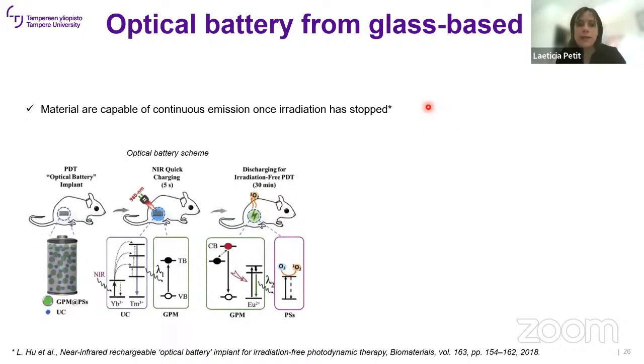The reason we are working on that is because we want to make an optical battery. So a few years ago, there was this very nice paper on a near-infrared rechargeable optical battery implant. The team worked on upconverter crystals, and they mixed them with persistent luminescent particles. Persistent luminescence is when you have luminescence after stopping the radiation source. By combining this blue upconverter with the green persistent luminescent particles, you can actually do photodynamic therapy in situ.